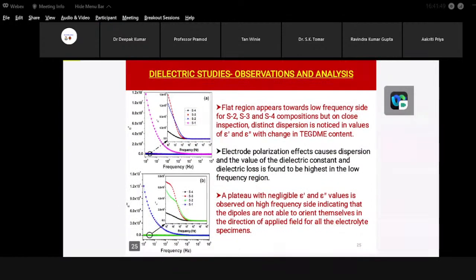So what we observe is the real part and the imaginary part of the dielectric have both been plotted as a function of the frequency for different electrolyte compositions. At the low frequency side, polarizing effects are observable, and because of it the value of the dielectric constant is high. For the dielectric loss also, such behavior is observable. It is very important to notice that at the higher frequency side the contribution is very negligible.